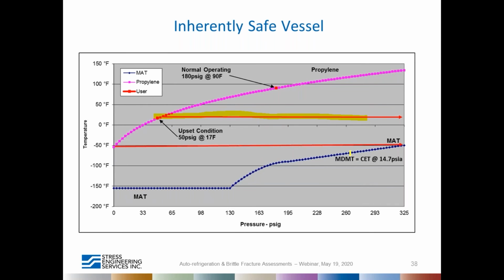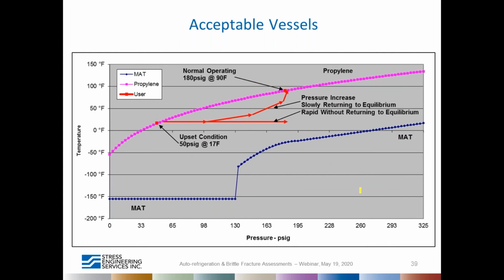So the pressure increases, that means you're increasing the risk of brittle fracture. However, while the MAT curve is still below this horizontal line, then the risk is minimized. In the other scenario where you just go all the way and de-inventory, where the pressure goes all the way to zero, and then you restart, the metal temperature is very low at this point, and yet if you repressurize it, you're still above the MAT curve. So this is an inherently safe vessel, and this is how you would do a process safety or process hazard analysis. Let's look at another vessel.